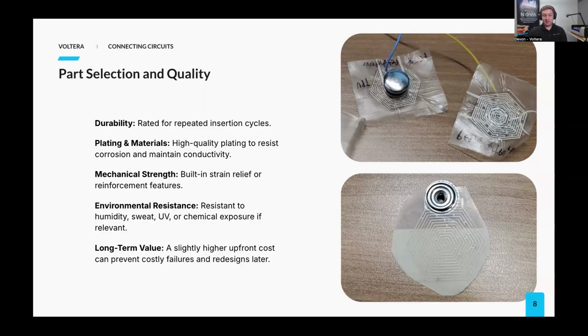Lower cost connectors often use thinner plating, less robust housing material, or fewer reinforcement options. This can lead to problems like poor contact retention, rapid wear, or even corrosion in humid environments. For example, in the gold ECG project, we utilized some low-quality snap connectors, which resulted in issues with signal fidelity and connector reliability. We initially thought our design had a problem, but it turned out to be just the snap connector. When we switched to better snaps, the issue resolved itself, and we were able to progress and finish testing and finish the project.